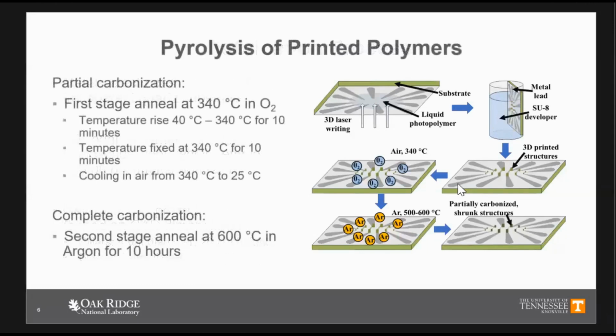steps. The first step of the annealing is basically a partial carbonization of the polymers, and that happens around 340 degrees Celsius in the presence of air or oxygen. The temperature usually rises from 40 degrees Celsius up to 340 degrees Celsius in about 10 minutes. Then we keep that temperature constant for another 10 minutes, and then it cools down from 340 degrees to room temperature. Then we place this sample in a rapid thermal processor unit, where it is annealed at 600 degrees Celsius for 10 hours in the presence of argon and at a pressure of 9.9 torr.